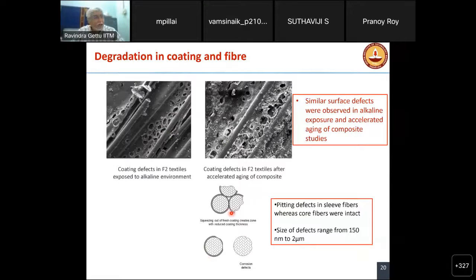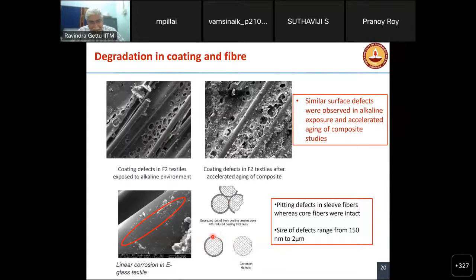Also, depending on how the textile is made, we can have some parts which do not have much coating because the yarns are bundled and later coated. And we find that in some places the coating does not penetrate, and you have this linear corrosion, linear type pitting which occurs in these regions. So in a region like this, you can have this pitting corrosion along the line. So it's similar to corrosion of steel, but this is corrosion in glass because of the attacks. And the coating sometimes does not help much. So the type of coating matters a lot. So we are working on the type of coating. We are seeing how the coating thickness matters and so on.